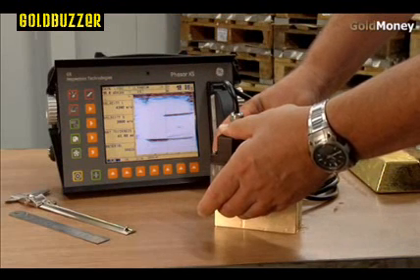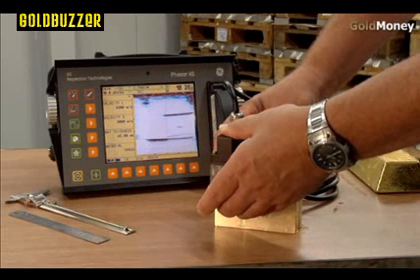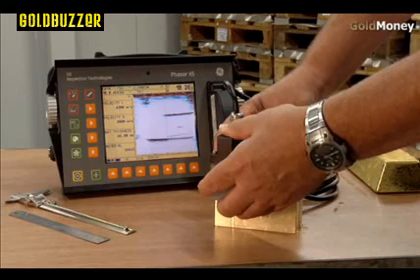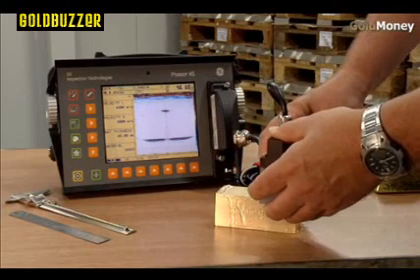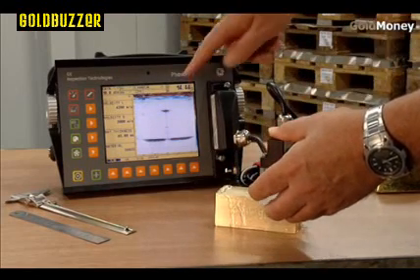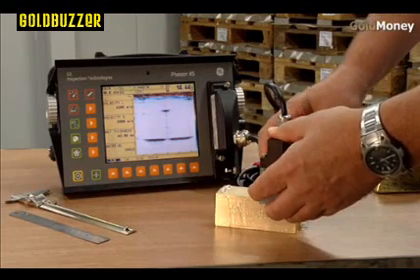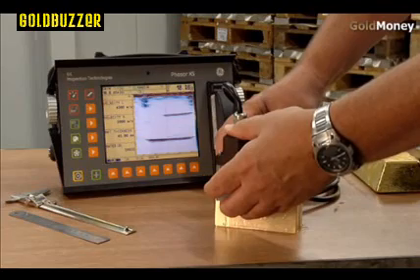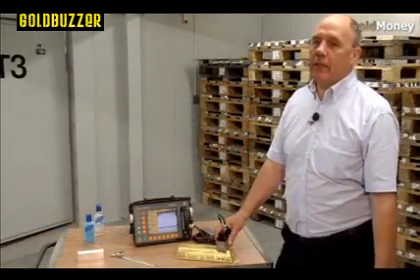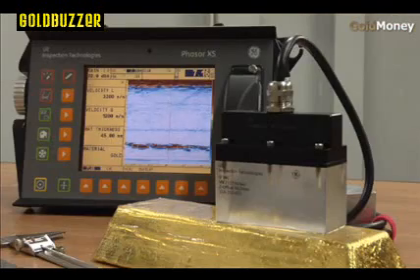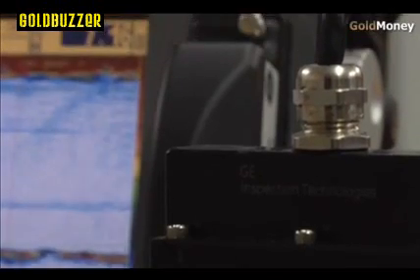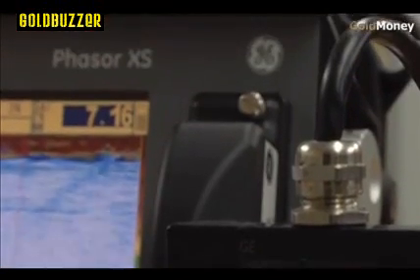That type of signal is what we would expect to see from an insert as opposed to a void. That would be the signal from a void — a small isolated indication. That would be the indication we would get from an insert. Ultrasound as a method for inspecting gold bars should give you a very high level of confidence that you would detect any discontinuities or contamination in the gold bar.